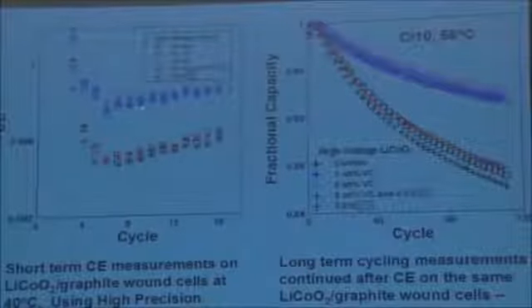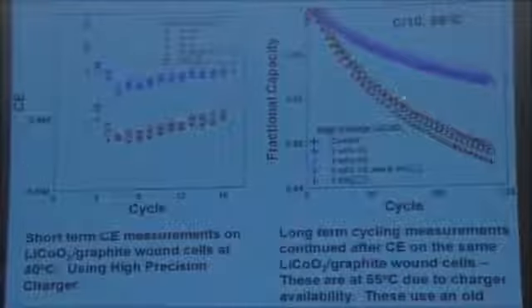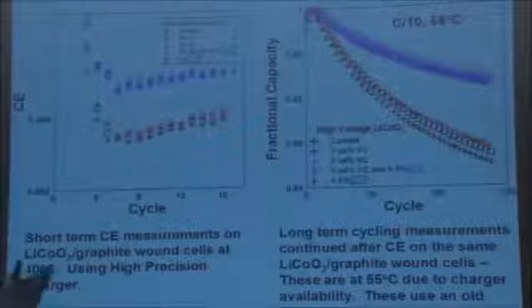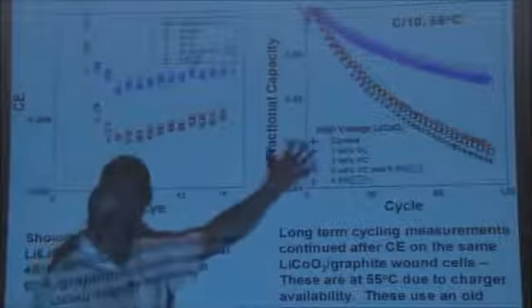And then these blue symbols are next, and they're next here. And the black is worst, and the red is next. So the point is, these short-term measurements bear out in the long term, right? So if you're somebody like me, and you're trying to make lithium-ion cells better, and you don't want to test for a long period of time, you do these high precision measurements and you can tell whether the electrolyte additive has helped or hindered what you're trying to do.